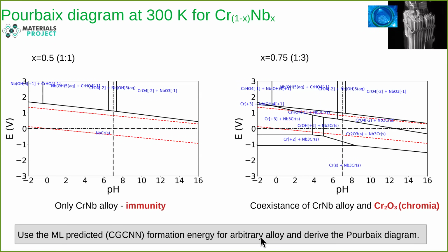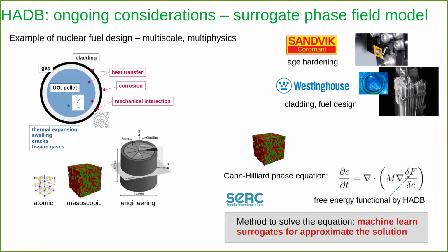Yeah. And then finally, I would like to also show one ongoing consideration, which is going towards the multi-scale situation. It's again collaborative work with the hard coating industry and also with the nuclear industry. Here we go for the phase field simulation, where we would like to use the thermodynamic information to evolve the mesoscopic phase of the material. So we are no more atomistic, but all the atomistic information is hidden here in the free energy functional, and that functional is known by HADB, or by the CGCNN model which we have.